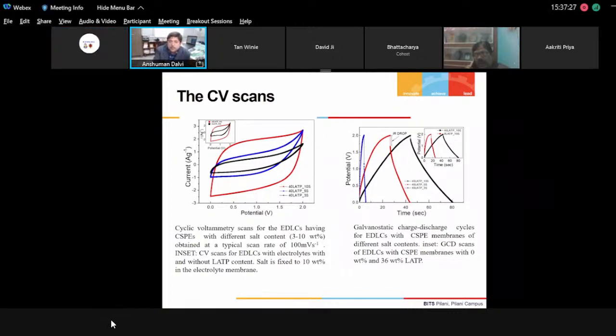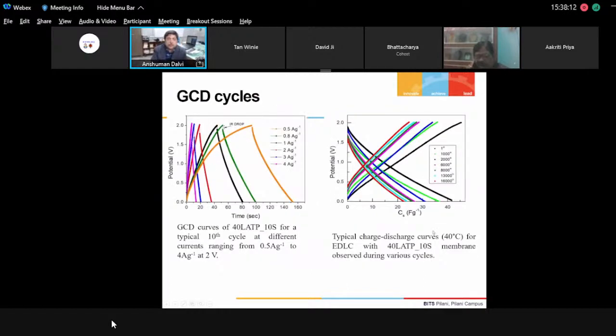That is also visible in the discharge curve, when potential versus time is shown, and various supercapacitor films were used, with various Nasicon content polymer films used as electrolyte. Then we could see that when the conductivity is high, we get a better discharge, and the discharge is almost linear, though not completely, but it's linear-like behavior. It is expected that a solid-solid interface will have a certain amount of polarization at various local levels. Therefore, it need not be a very smooth and straight line drop of the potential, but the nature of the overall fall suggests that this is indeed a supercapacitor formation.